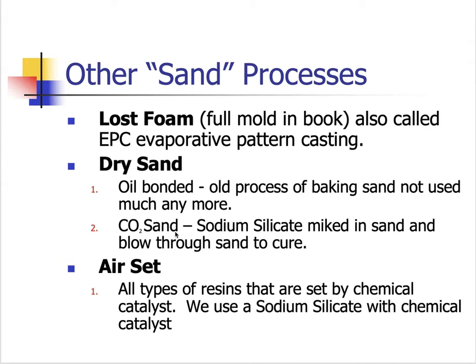We do this in our lab. So you mix sodium silicate with sand. It makes kind of a wet sand, feels just like sand on the beach. And then you pack it into a mold, and you blow CO2 through that sand with like a little suction cup or blower kind of thing. You actually blow CO2 through the sand, and now you have a cured, really hard mold. Okay,